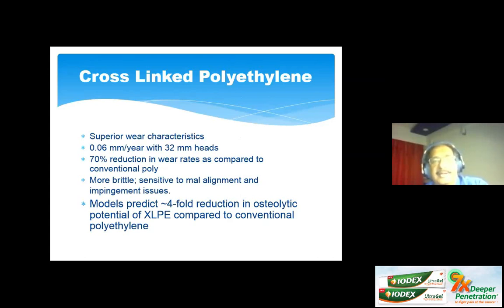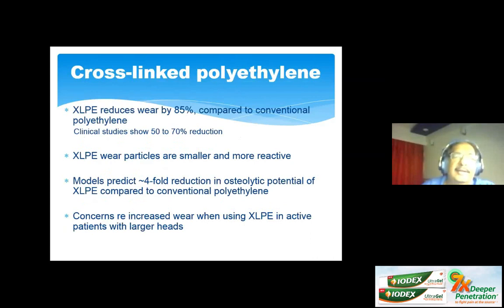It is more brittle. It is sensitive to malalignment compared to the old polyethylene, and there is up to a 4-fold reduction in osteolytic potential of the highly cross-linked polyethylene compared to the conventional polyethylene. Clinical studies have shown a 70% reduction. Sometimes the highly cross-linked polyethylene particles are more reactive, but definitely smaller. There are concerns regarding increased wear when using highly cross-linked polyethylene in active patients with larger heads, and this is more when we are using heads above the size of 32.